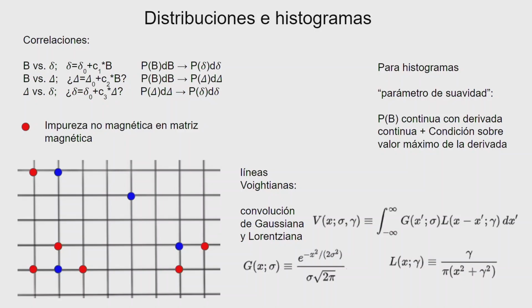In this case, for example, if you assume that you have a distribution of magnetic field for 20 values, you have to consider maybe 20 values of isomer shift. 20 plus 20 is much more than the number of experimental points. So you have to reduce. And of course, the linear correlation is not physically elegant, as you mentioned, but it is not too bad. It's like solving a single equation with two unknowns. Anyway, as a general rule, at least the one I use, the fewer components that I can fit in the spectrum, the better. It must be a rule.